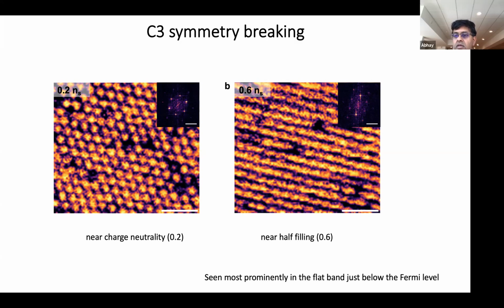Yeah. Okay. Yeah. Thanks. Well, maybe there is a little bit of nomenclature. I guess, Abhay, when you say charge density wave, you would like to see a Q vector which is not already present. That's right. From a purity point of view, if you see a ferromagnet, it's also intra-unit cell ordering, and yet it's spontaneously broken. So one could argue that what you see abundantly does look like a charge density wave, which just happens to have the same periodicity as that of the moiré, and so it doesn't break any additional symmetry.